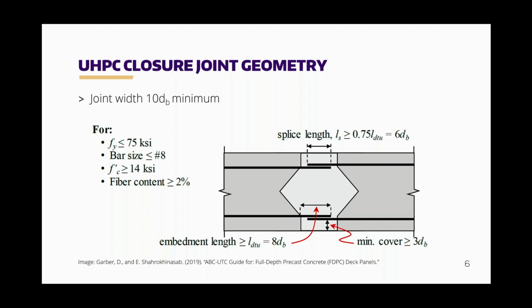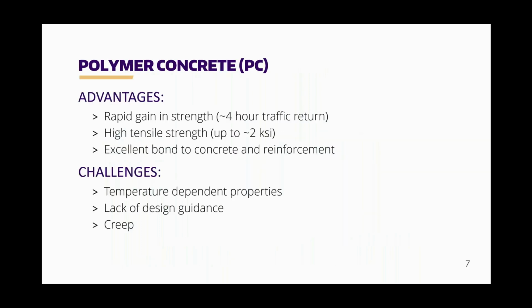One of the challenges with UHPC and all cementitious materials is that the rate at which they gain strength is controlled by the hydration of that cementitious binder. And so for an application where you need strength quickly, very quickly, in a matter of hours, there may be alternative joint materials that would be worth exploring. And one option for that is polymer concrete. The advantages is that you get a rapid strength gain, about a 4-hour traffic return is possible, so perfect for an overnight closure window. You have a high tensile strength comparable to UHPC, up to about 2 KSI, and you get excellent bond to concrete and reinforcement.